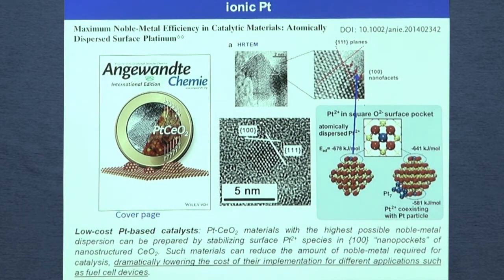And the explanation is here. In this Angewandte Chemie paper, which we published a few years ago, this is the cover page, by comparing the experiments and doing DFT calculations, we propose that the high stability and activity of the catalyst is due to the anchoring of single platinum ions between square oxygen nanofacets, the (100) nanofacets, on ceria nanoparticles. Because even if we are using thin deposition, it's polycrystalline. We are forming a layer composed of nanoparticles of an average 5 nanometers with different surface planes.